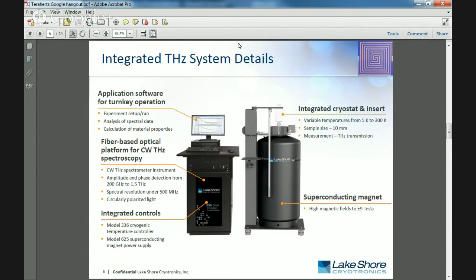Yeah, so what we wanted to do is think a lot about how researchers need to approach these terahertz measurements. And so environment is really key. So what we've done is we've taken the terahertz transmission measurement and coupled it into an integrated system. The system consists of the cryostat, which allows sample measurements from around 5 Kelvin all the way up to 300 Kelvin. That's surrounded by a 9 Tesla magnet. This whole cryogenic and high magnetic field platform is supported by an instrumentation rack and a spectrometer, which sits there on the left side of the slide.